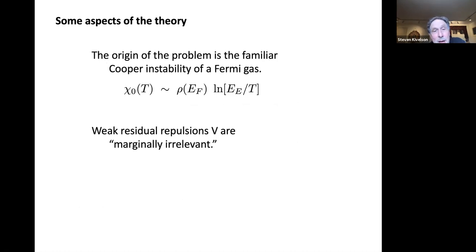And the reason you might think it would become a superconductor is because the superconducting susceptibility of a non-interacting Fermi system has a logarithmic divergence. And because of Anderson's theorem, this logarithmic divergence survives even in the presence of disorder. The only thing that would cut this off is when the temperature got below this temperature scale I defined at which localization starts to be important, which, when the resistivity is tiny, we can neglect.